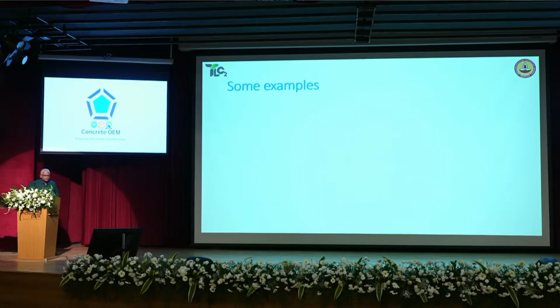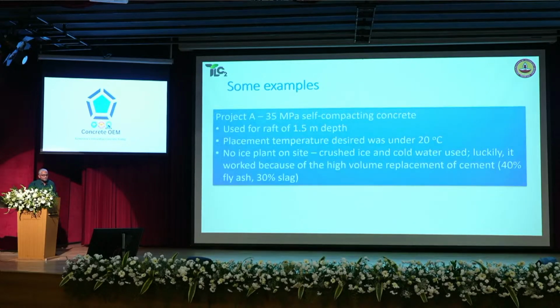Some examples I'll give you again of site-based control where it led to problems. In the first project, 35 megapascal self-compacting concrete was used for a raft of 1.5 meter depth. Placement temperature desired was under 20 degrees Celsius. So here the spec said, you have to make concrete under 20. There was no ice plant on site, but crushed ice was supplied.